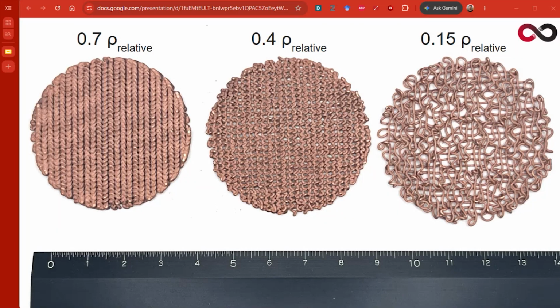And so here are a few examples of what a few densities of our copper foams look like in a thin form factor. So ranging from high 0.7 relative density on the left, to a moderate 0.4 relative density in the middle, and a low 0.15 on the right. You can see how our foams are entirely composed of those entangled coils. It's basically one continuous thread bent upon itself for the entire body.